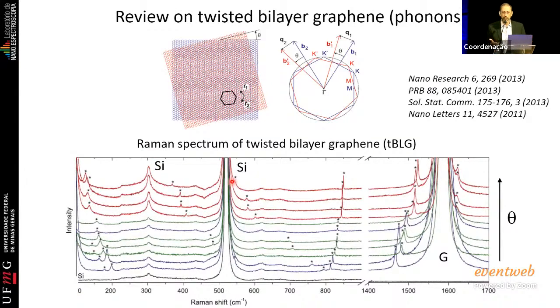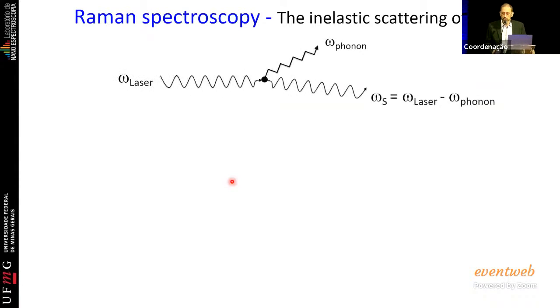Every time you have a two-dimensional material, usually it's sitting on a substrate, and you also see the substrate. But let's take a step back. What I was showing you was the Raman spectrum of twisted bilayer graphene. So what is the Raman spectrum? If you shine light on the material, the photon may lose energy to a quantum of vibration in the system, a phonon, and the scattered light will be shifted from the incoming laser light by the phonon energy. So by studying the inelastically scattered light, you have a lot of information from the material.